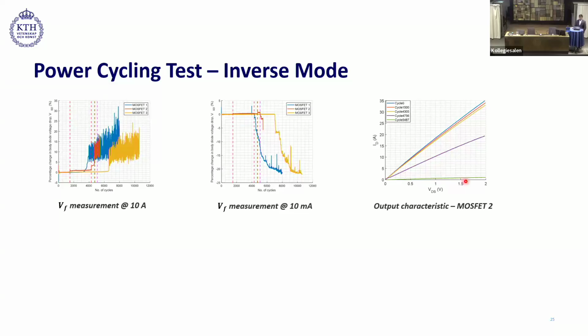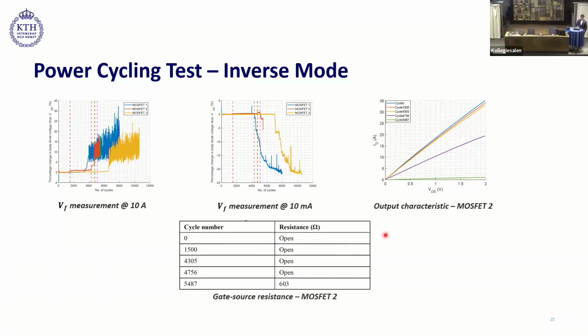So we were interested to see what happened here. So we also measured the gate to source resistances, and we observed that at the end of the test, the gate to source resistance changed from open to 603 ohm. So we estimated that the device has failed because of shorting of gate and source terminals.